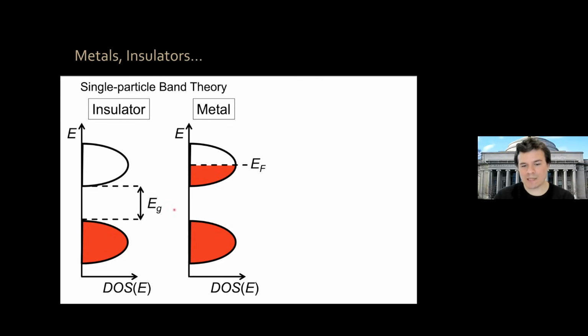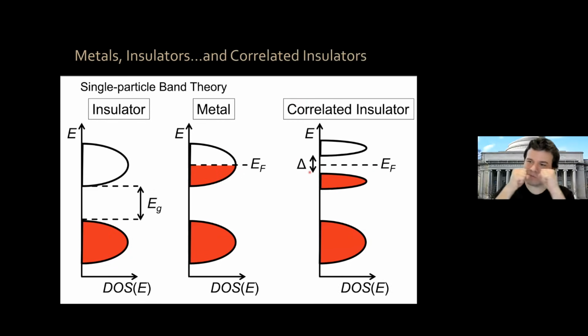For example, we can be in a situation similar to this one, where we have one band which is half occupied with electrons. Okay? But now, due to strong Coulomb repulsion between your electrons, that band splits into two, okay, with a correlated gap in between. It's not a single particle band gap, but a correlated gap in between these two bands. But you can see that because this band was half occupied, this splitting into two bands now leads to a situation which is very similar to this one. You have one band which is completely occupied and one band which is completely empty, and there is a gap in between. And therefore, the system actually goes into an insulating state, but it's not due to single particle physics, it's due to correlations, okay?